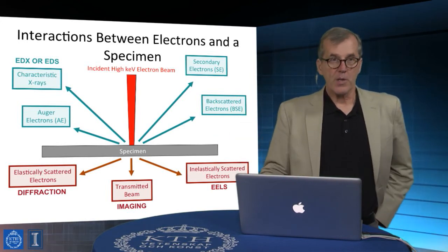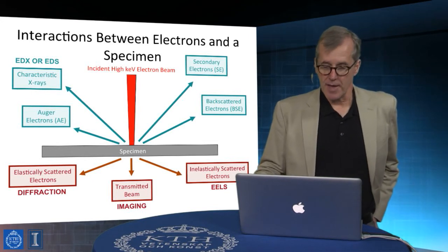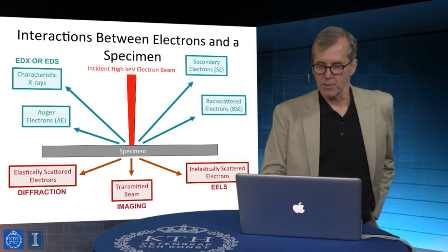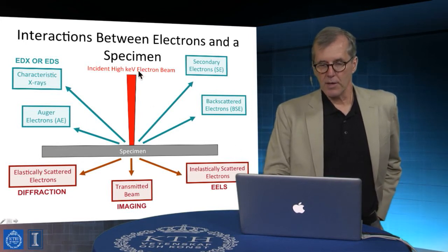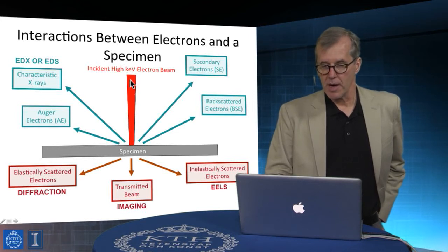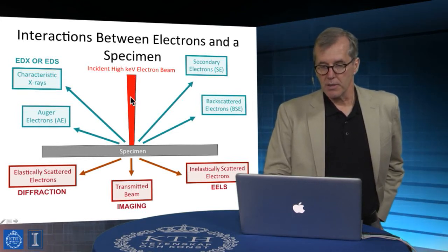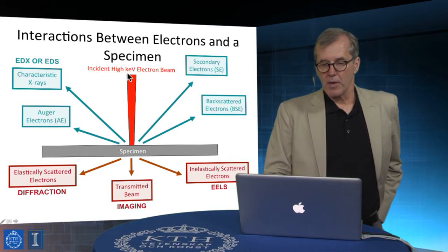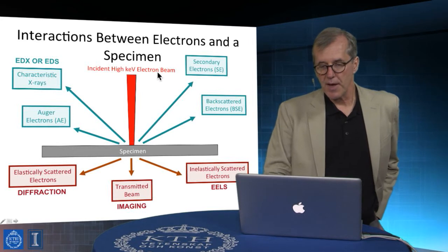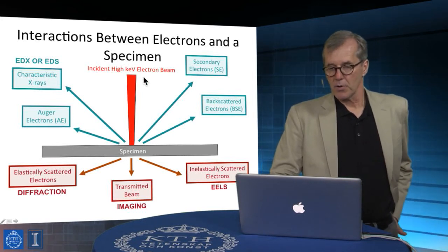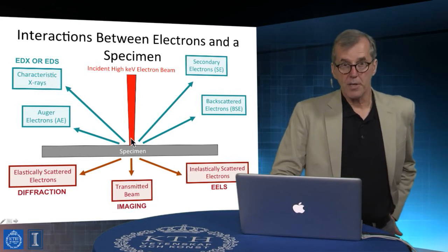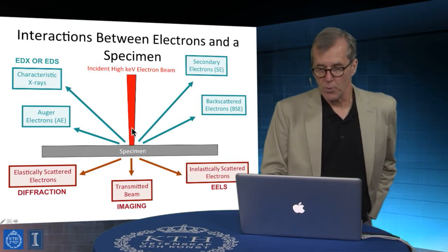Okay. So let's think about how we would describe the hierarchy of excitation, or the probe event, and all the things that we can do subsequent to that, that would provide us some understanding of the structure of a material. So we have an electron beam, and this will be a high energy electron beam, like for example several hundred thousand or several tens of thousands of electron volts. And those accelerating voltages are needed to provide electrons with very short wavelengths.